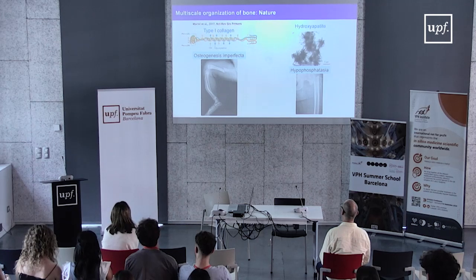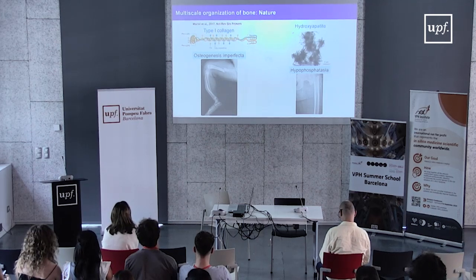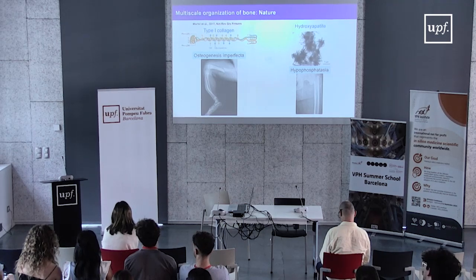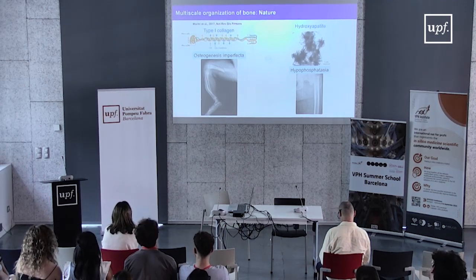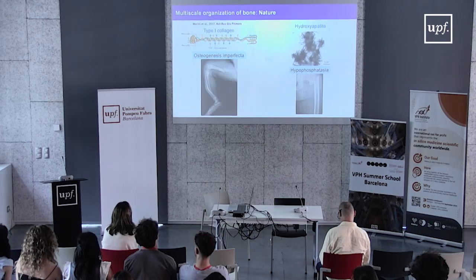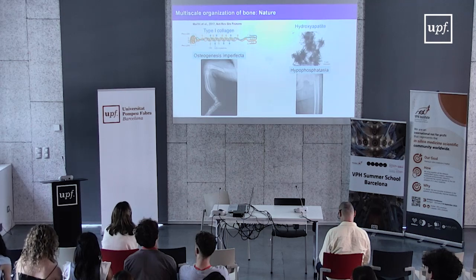It's specifically seen in infants around 2 to 3 years old. When they start to walk, they fall down and they will break their bone. And you see, it's not the classical fracture that we can see in osteoporosis, but really a fracture in the middle of the femur, which is normally the place where you have only cortical bone, so a strong and compact bone.